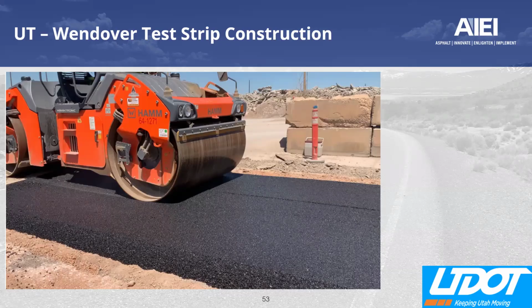Okay, thanks. And then a related question that came in was, if you do have some RAP that's this high polymer mixture RAP, can you put that back in a premium surface layer? I'll jump on that one to begin with. As I mentioned, the state of Utah allows up to 15% RAP in their mixtures. Again, that's by mass, not by binder replacement. And this is a first for the state. So again, I would not hesitate to utilize highly modified RAP in the future in surface mixtures. One thing to be careful with is making sure that we don't push the RAP limits too high too fast. Let's make sure that we do engineer them. And an entirely other topic is the whole issue of rejuvenation, and we could go down a rabbit trail on that, but I'll stop there.